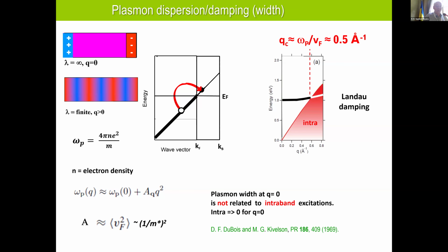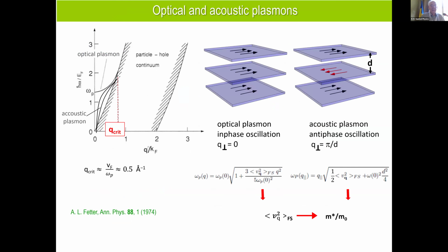And so when you measure the dispersion, you can get information on the average Fermi velocity, and this depends on the effective mass. So you can get information on the renormalization of the band structure. Now in some cases things are even more complicated, because you not only have the optical plasmons at high energy, which are gapped.